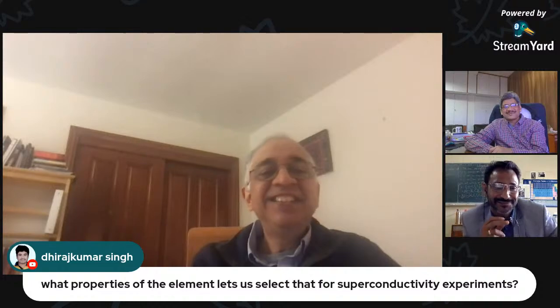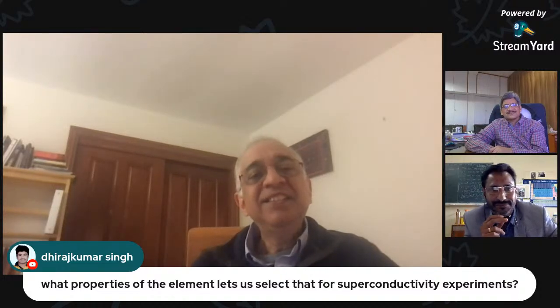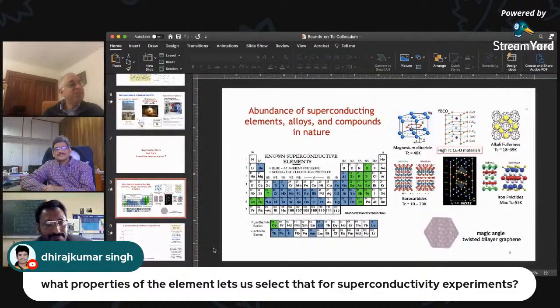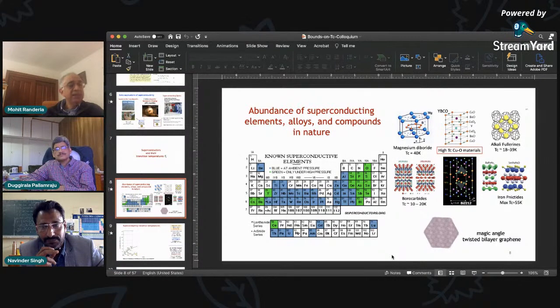I don't have a slide, which I wish I did. In the early days when people understood superconductivity in elements, they basically said that cubic systems are the best, three-dimensional systems are the best, avoid oxygen, and avoid magnetism. Those were the rules of thumb that solid state chemists used. They were called Matthias's rules. Of course, the last rule was avoid theorists. And the jury is still out on whether that last rule is valid. But all of Matthias's other rules are completely wrong.